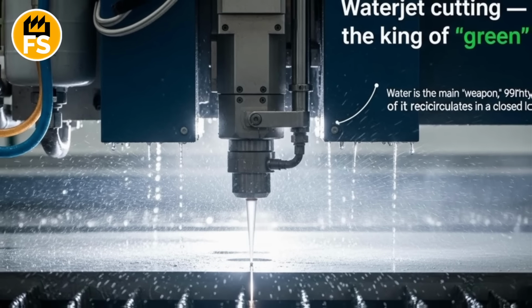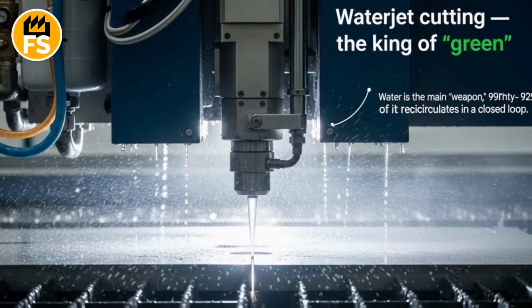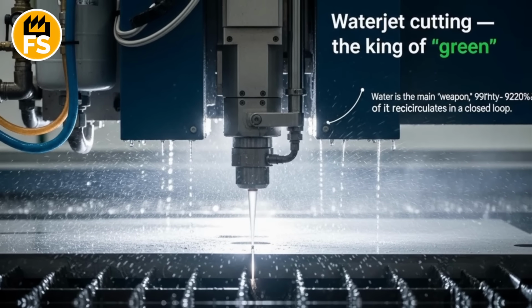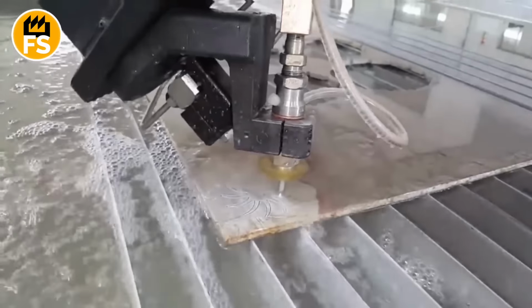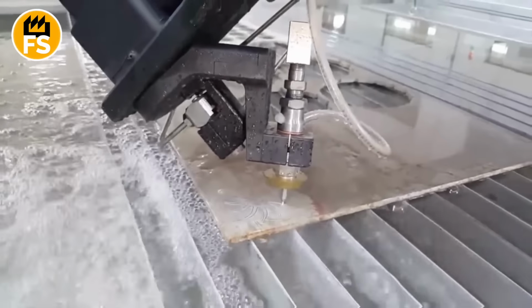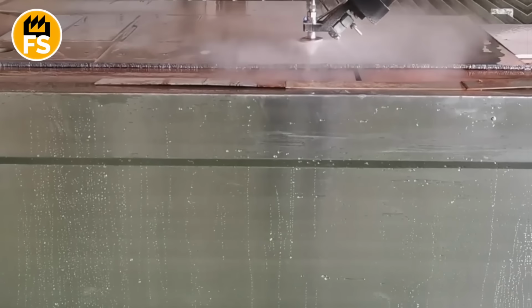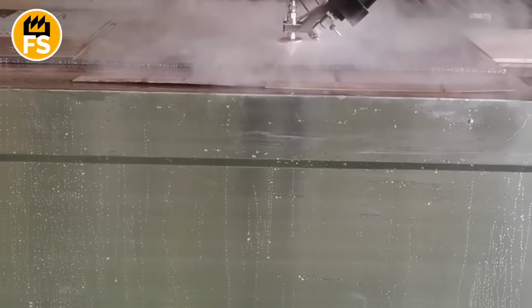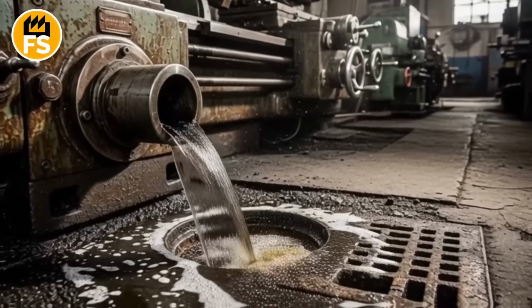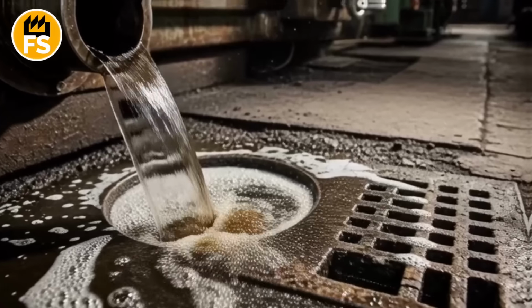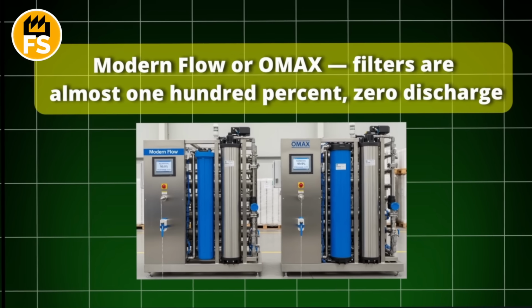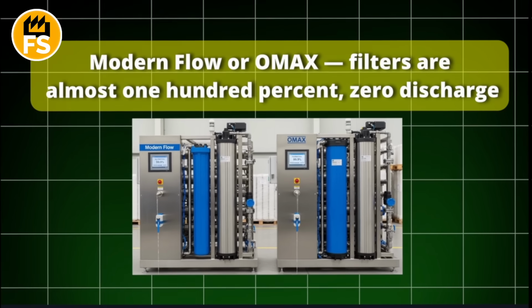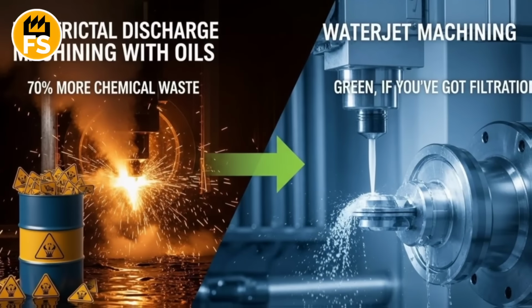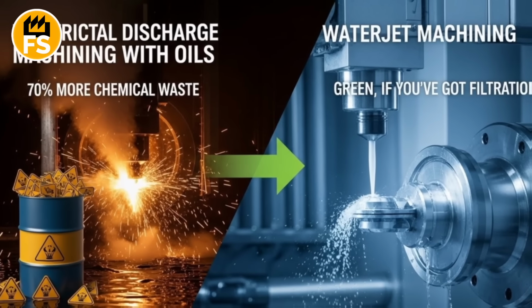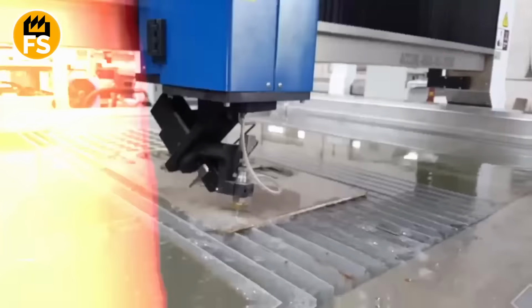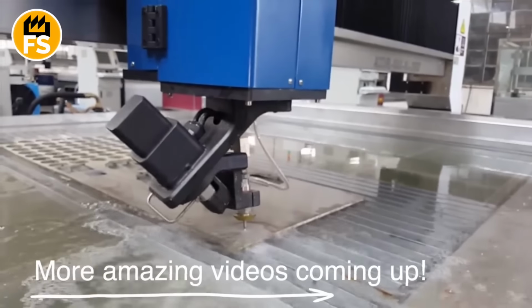Water jet cutting, the king of green. Water is the main weapon—99% of it recirculates in a closed loop. Garnet abrasive, a natural mineral, non-toxic, gets reused up to 10 cycles. Energy, 30 to 50 kilowatts per hour, less than laser. But here's the catch: old machines dump dirty water into sewers with metal dust. Modern flow, or OMAX, filters are almost 100% zero discharge. Fact: Boeing cut chemical waste by 70% with water jet versus electrical discharge machining with oils. Verdict: green, if you've got filtration.